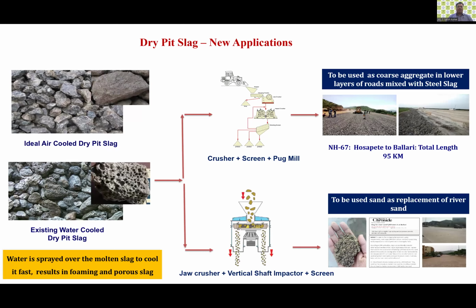During the iron making process, we also get some amount of coarse slag or solidified slag in the pit. This can also be processed and utilized either as coarse aggregate, or we can crush it and utilize it as fine aggregate. We have done both these exercises at JSW Vijayanagar Works and on NH-67 Hosapete to Ballari Road. A lot of this crushed dry pit slag from the blast furnace has been utilized in road construction. We also crush it to very fine pieces, and a fine aggregate has also been made using this material. These technologies are now commercially established and running at Vijayanagar Works.